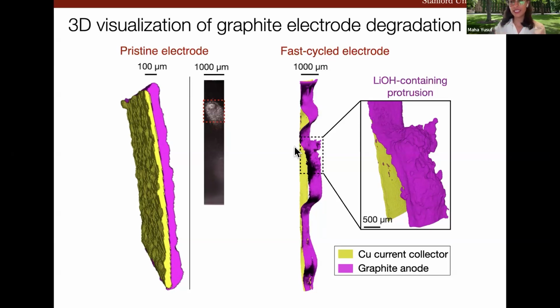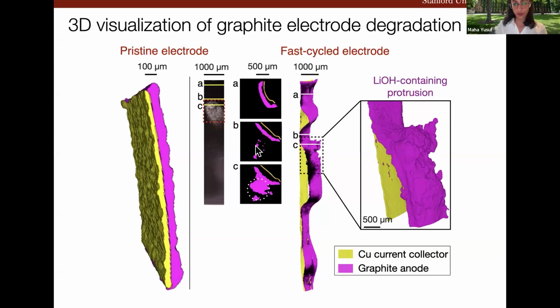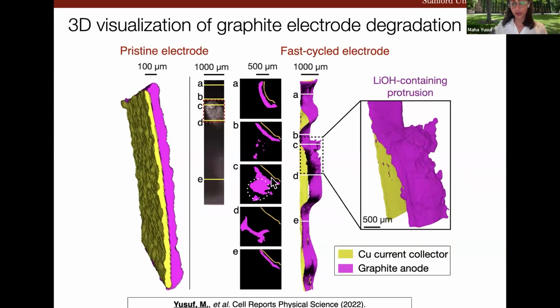And because this is 3D data, we can also correlate these colorized segmented slices as a function of depth of the electrode. What I mean by that is here, slice A corresponds to the thick yellow and white lines labeled A on either side. Same goes for B and C, where we can visualize this lithium-containing protrusion very nicely. And in D and E, where we are going away from this protrusion, you can see the delamination of the current collector from this graphite.